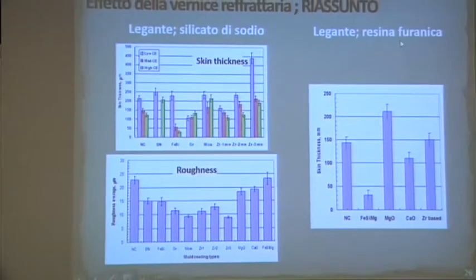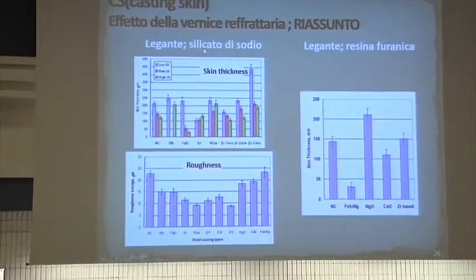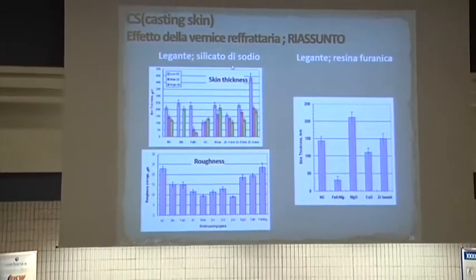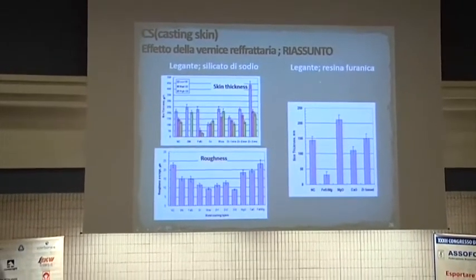And when you have a resin, so this is for silicate bonded mold, you have very different effect depending on the mold. And this is for the furanic resin bonded mold. And you can see here the most efficient is ferrosilicon magnesium. You have sulfur in the resin bonded mold, so you have to counteract the sulfur. You don't have sulfur in the sodium silicate, mostly oxygen is the reason.